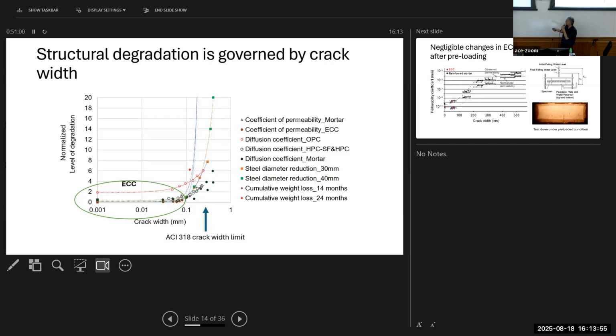Okay. Now, what is also interesting in this chart is the ACI code, the building code 318, at least the older version, used to have a specification of crack width limit. And it's about here, okay? It varies a little bit left to right, depending on whether the structure is indoors or outdoors. There are two different specifications, but roughly it's around here. And what is interesting, and the reason why I point that out here is this is very close to the elbow point. So sometimes you can design infrastructures that are below that point, so you are out here, and degradation is very small, so they maintain very well. But just a little bit above here, then you get this very fast accelerating degradation. And this is the problem, a lack of reliability.